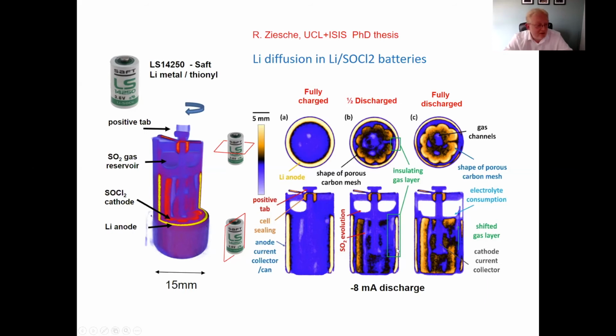And what you can see is the diffusion of the lithium metal as you go from the fully charged to the discharged. And you can see the creation of these white patches, which are SO2 gases that build up within the battery, which may degrade the performance of the battery over its lifetime. But the tomography gives you all of this information. Admittedly, this is a 3-day experiment to collect all of these images, but it gives you all of the internal information of this battery dynamically, in operando, without having to cut it open.